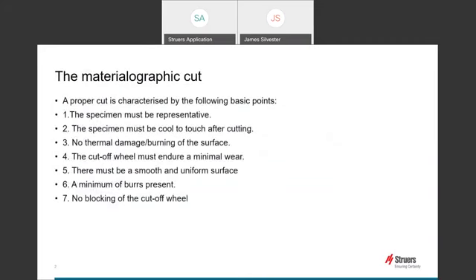For us to say we have a proper cut, we should meet the criteria shown on the screen. But the main points are absolutely essential, and they are that the specimen must be cool to the touch after cutting and have no thermal damage or burning to the surface. The sample being cut shouldn't grab the wheel during cutting or cause blocking of the cutting wheel, as nearly all wheel breakages are caused by improper clamping techniques and practices. If we clamp the sample correctly, you stand a better chance of getting the part you need, minimize subsequent grinding operations, and help speed up the throughput and reduce consumables cost through fewer wheel breakages and breakdowns.